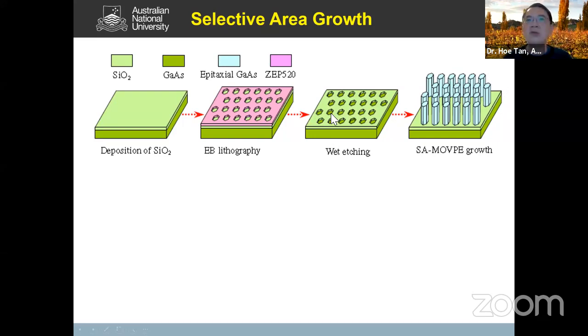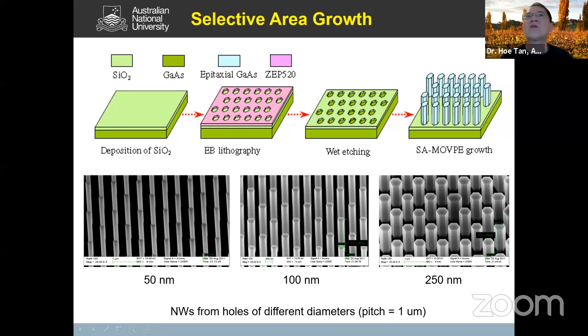And the beauty of this technique compared to the VLS growth is that it can grow very regular arrays, as you can see here. This is a 50 nanometer opening, and you can see the nanowires are very regular. This is 100 nanometer and 250. Again, on a single wafer, you can create all the different diameters that you want. So this is a very powerful technique, selective area growth.